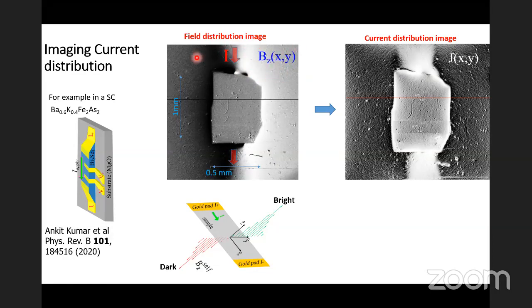So this is the distribution of the local field which is generated by the current, and we image this sort of a local field. And we can do a numerical inversion, somewhat like an inversion of the Biot-Savart law, to get the current distribution. So this image shows the self field inverted to get the current distribution, and this is how the current is distributed across the sample. This is a superconductor, through which you can see that the current comes in. There are strong currents on the edges, there are currents also inside the sample, and these regions outside are the contacts. They are carrying uniform current. So this image is to give you an idea of what you will be seeing when we start looking at the images of the topological insulator.